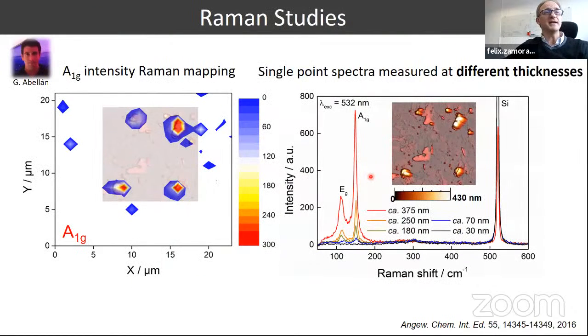We also used Raman in collaboration with Gonzalo Abellán to characterize our layers. And here you can see that it's something not very usual. We were unable to detect any Raman signal from the two big characteristic modes of antimony. If you check carefully here, we were unable to obtain any Raman signal below this thickness, below 70 nanometers.